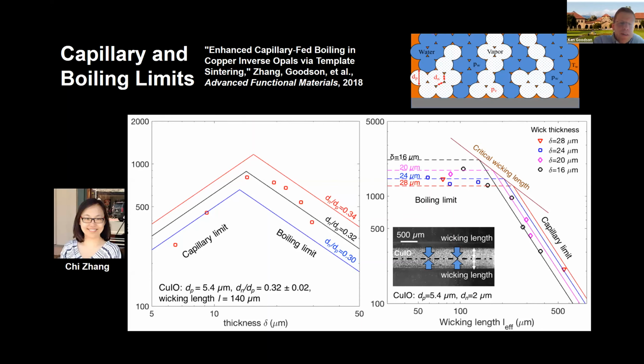So it was a very sensitive way to control the pore size by means of the polystyrene sphere size, but she was also able to control very carefully the neck size connecting the two. And it allowed her to do some really interesting investigations of the physical limits that are associated with convective devices.